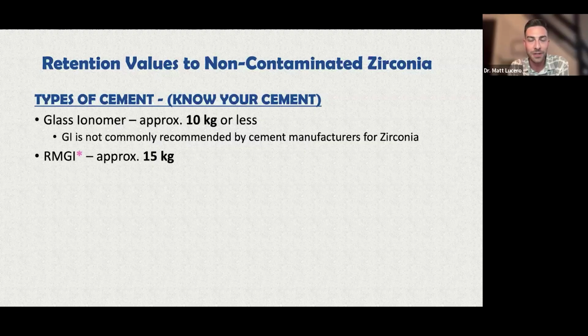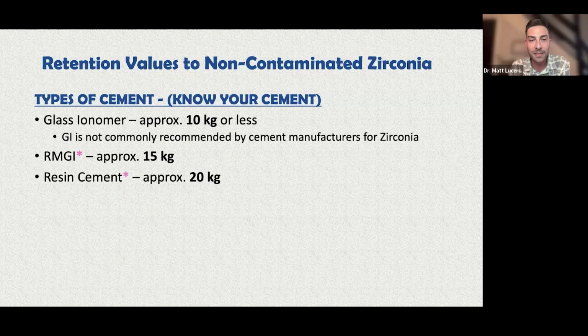There's RMGI, which, Fujicem 2, Reliax, there's other manufacturers that make an RMGI as well. That's a really good option. I like RMGI in certain scenarios, especially in the posterior. If I can't get my curing light back there, I'll talk about Biosem in a little bit. That's a dual cure cement. But if I can't get my curing light back there, or if it's a little bit tight, then an RMGI works really well. I just got to hold those crowns in place while the RMGI sets up, which takes a couple minutes. There are resin cements as well, which have a little bit more bond strength.